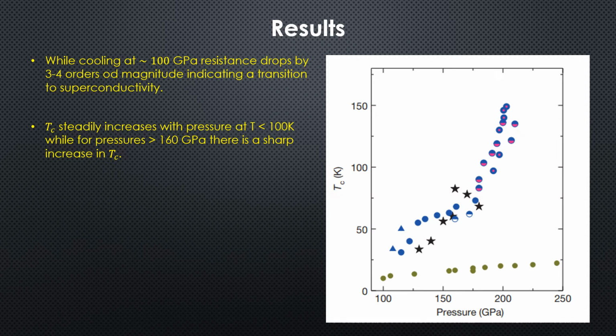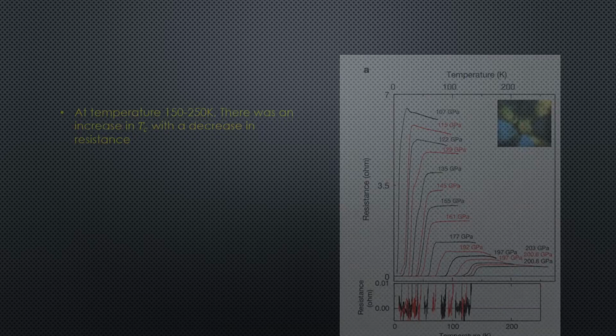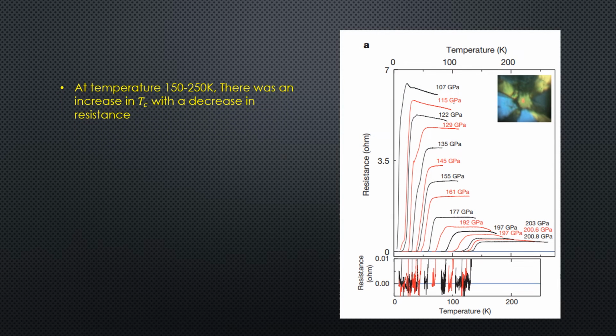As you can see from this graph, at temperatures between 150 to 250 K there was an increase in Tc with a decrease in resistance of the material. It was also found that Tc was strongly dependent on the isotope, and the lowest Tc was observed for the sulfur deuteride isotope of the sample.